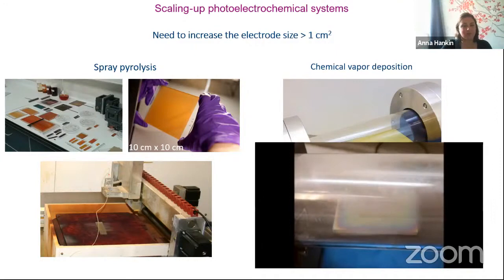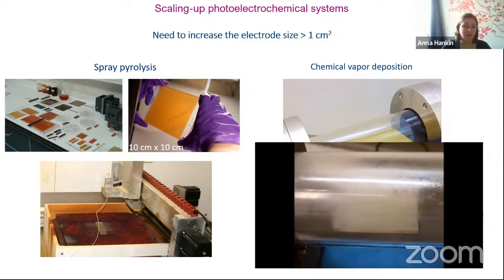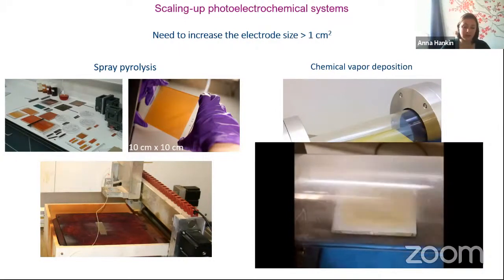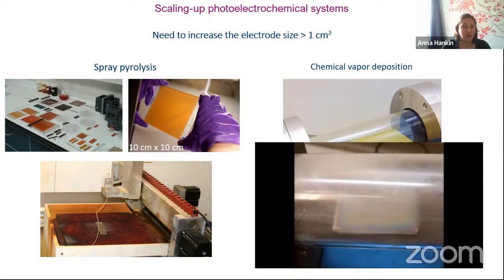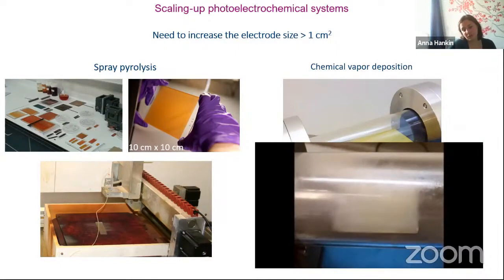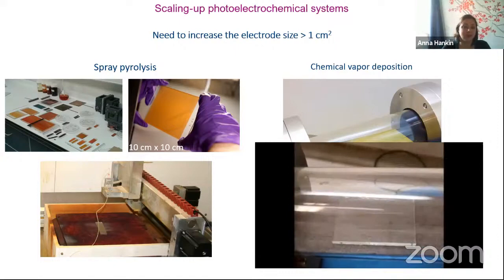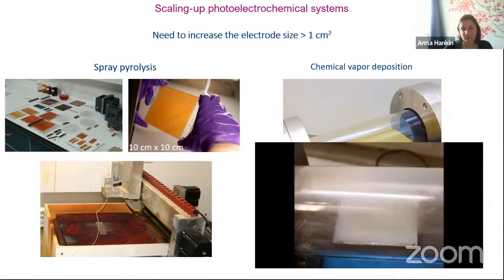So it means that you can irradiate the deposited material from the front or from the back, and you have a lot of flexibility regarding that. And also these materials, the transparent conducting oxide, they tend to form adequate junctions with almost any material that you put on top, and they don't themselves participate and they don't catalyze the reaction. So it's very useful to use this kind of substrate for the initial experiments, but it does pose some issues when you actually come to put it in a reactor.